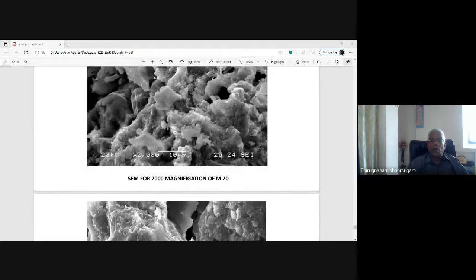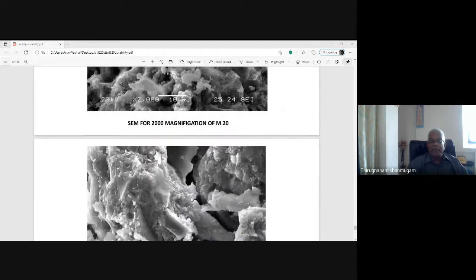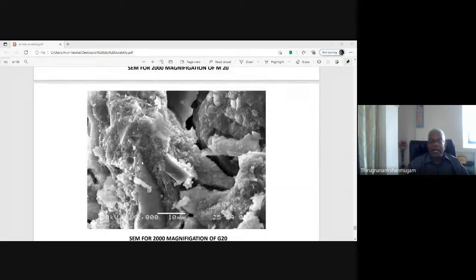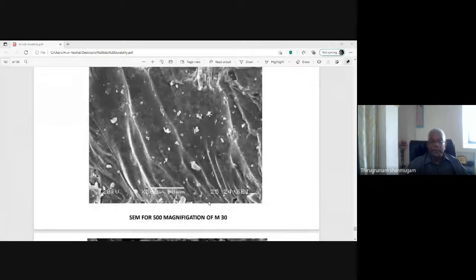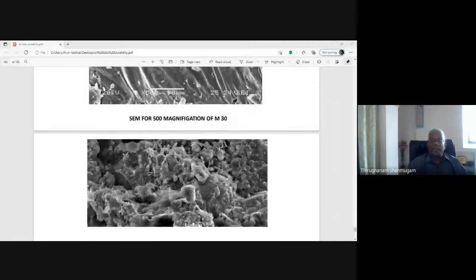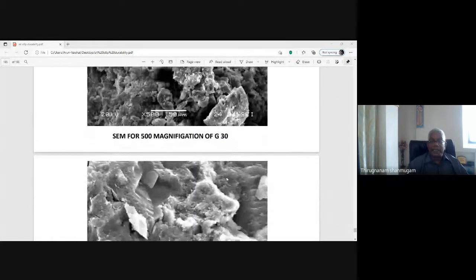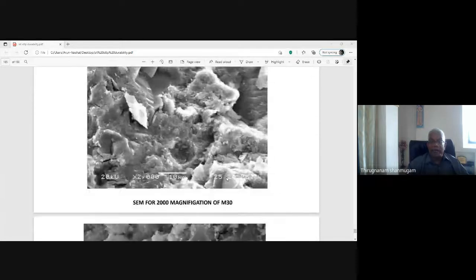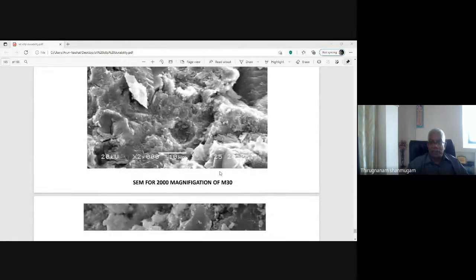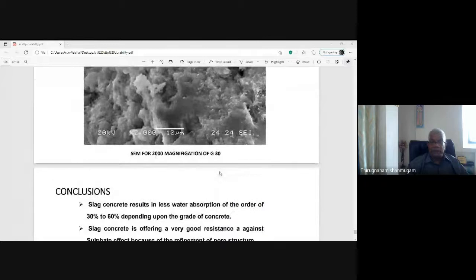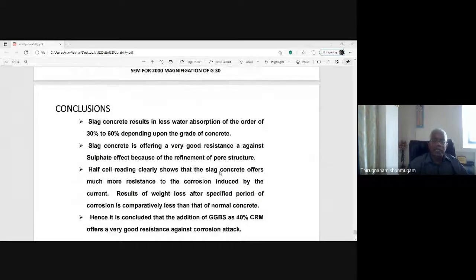The black holes, what are they? Here the black spots are very limited and the gel formation is very, very high, up to the maximum percentage. This is for M30 concrete, high strength concrete, and G30 concrete, at 2000 magnification, gel formation like this. So based on this, the conclusion is slag concrete is offering a very good resistance against sulfate effect